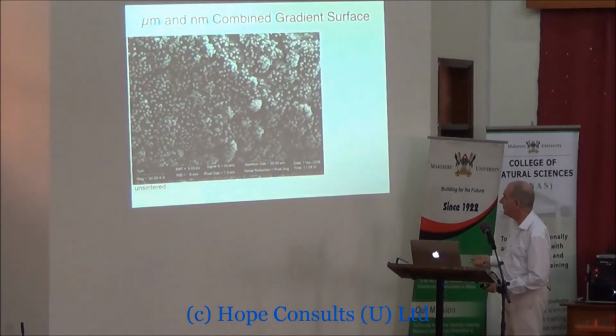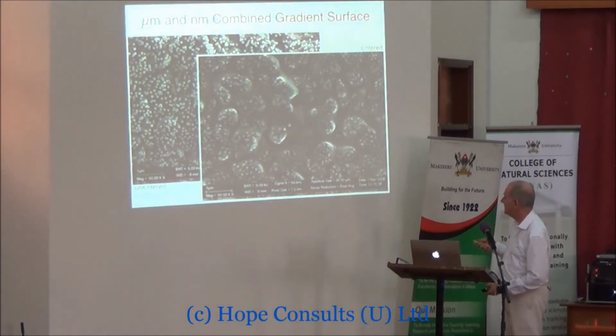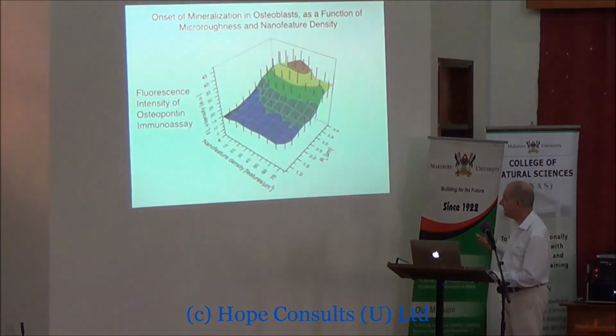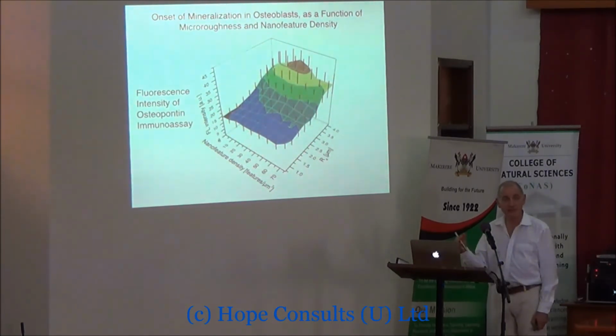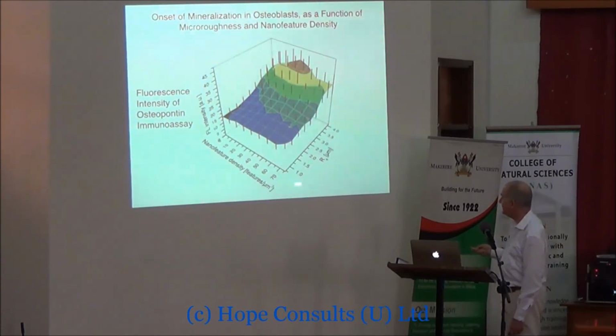And this is what it looked like before sintering. This is what it looks like after sintering. And then this is what the results look like when we expose it to the bone cells, and we start to measure what's called osteopontin, which is a marker for whether the cells are starting to mineralize, starting to make bone. And you can see that as you change, this is the microscale gradient, this is the nanoscale gradient, as you go up in roughness in the microscale gradient, you get more and more osteopontin produced, so more and more bone mineralization is happening. So the micrometer scale roughness seems to be important.